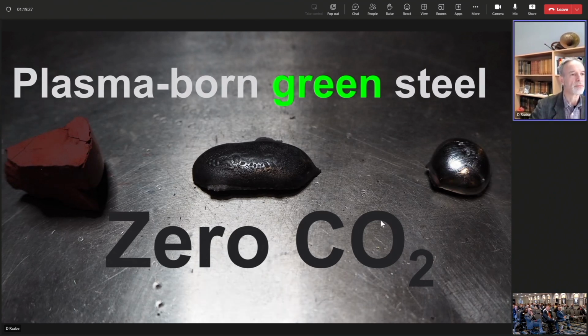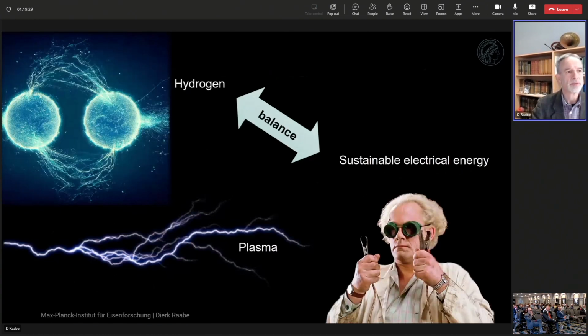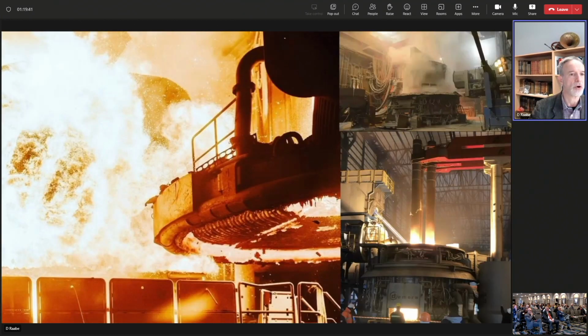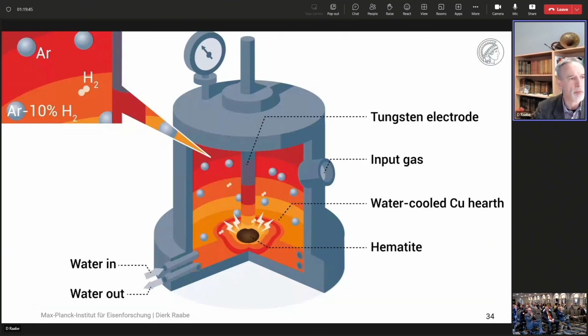So the idea of plasma-based reduction is that balance between the consumption of hydrogen and the consumption of electrical energy. Because as I said before, you must always balance your resources and be flexible. So that can be done in existing electric arc furnaces that you all know for scrap remelting. And the idea is to equip them with a moderately reducing atmosphere. Here you see argon and hydrogen. We take only 10% hydrogen and even do experiments with even less.